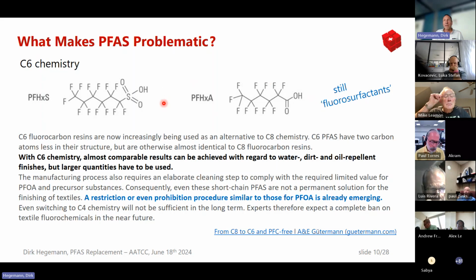And if you remember the very latest results from the measurements, what you find in the Great Lakes, you still find the long chain, but now you also find all the shorter chains related to the replacement with the shorter chain chemistry. So that doesn't help a lot. You get almost comparable results. However, larger quantities have to be used. So it's not really a situation you like to have. You replace one PFAS with other PFAS and even need more of them to get comparable results.